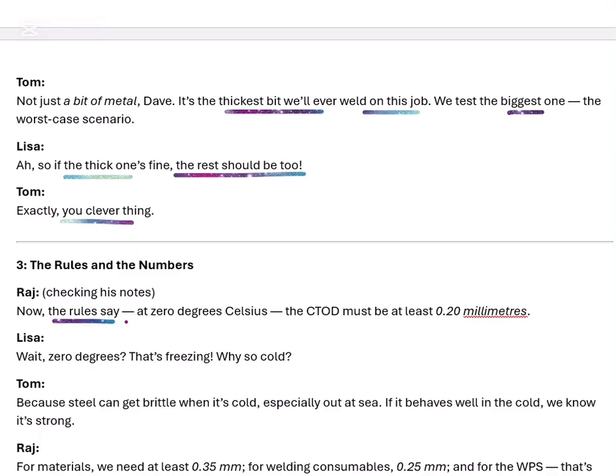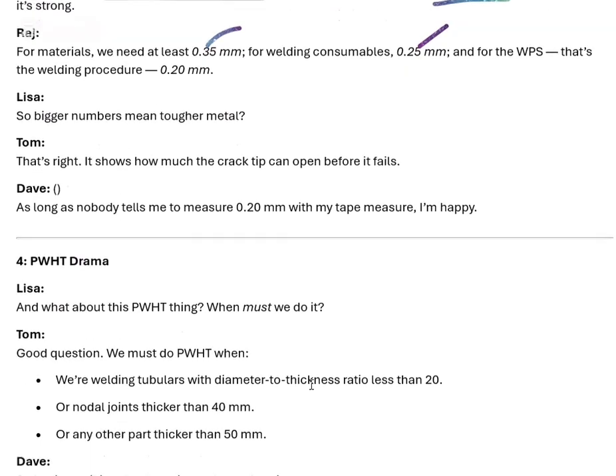Now the rules say at 0 degrees Celsius the CTOD must be at least 0.2 millimeters. Wait, 0 degrees? That's freezing. Why so cold? Because the steel can get brittle when it's too cold, especially out at sea. If it behaves well in the cold, we know it's strong. We need at least 0.35 mm for materials, 0.25 mm for welding consumables, and for the WPS, that's the welding procedure, 0.2 mm.